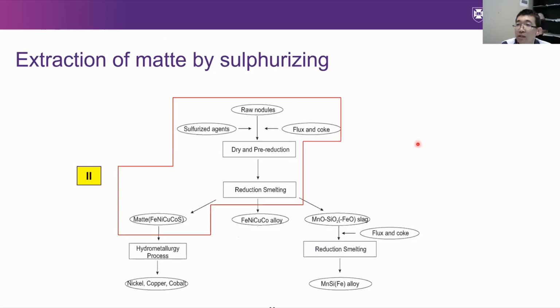In the second stage, instead of making ferroalloys, we add some sulfur agent to produce iron, nickel, copper, cobalt matte. This matte should be integrated with a hydrometallurgical process, and then finally produce pure metals.